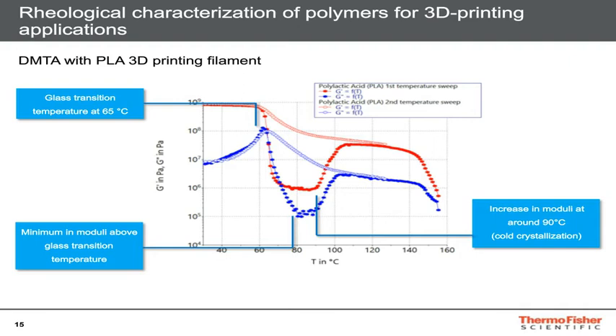Now let's have a look at the unfilled symbols. They represent the results of a DMTA test performed with a PLA filament with a different thermal history. Prior to the test, the specimen was heated up to 130 degrees centigrade, so above the cold crystallization temperature, and afterwards cooled down below the glass transition temperature, but slowly with a rate of -2 centigrade per minute.